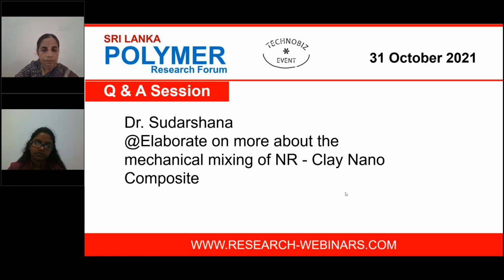But my point is, we normally add the clay into rubber with the minimum number of clay layers. That means 20, 10, 5 clay layers in the stack. At that time it is effective. But if you add a very large clay particle into latex, it is very difficult to separate clay layers. So once you add the clay into the latex, the clay stack should have a very minimum number of clay layers. That's my point.